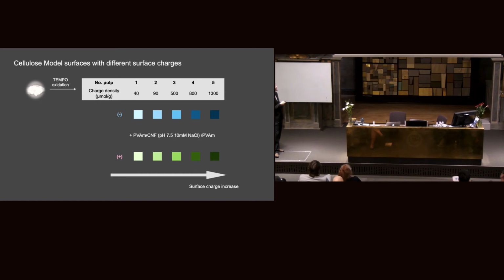At this condition, the CNF works good, but also keeps as few aggregates as possible. And then we get these positively charged surfaces with an increasing charge gradient.